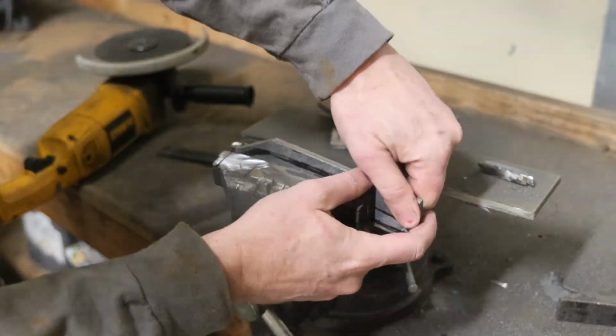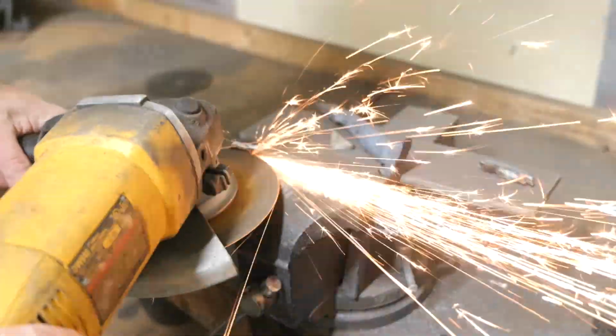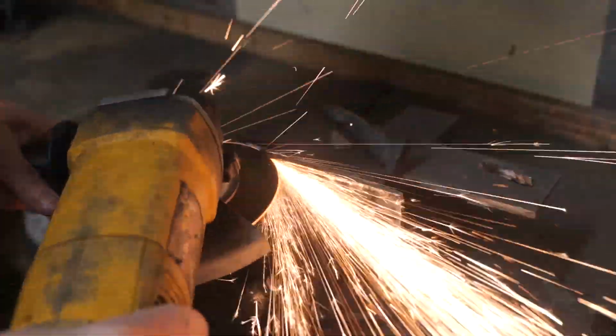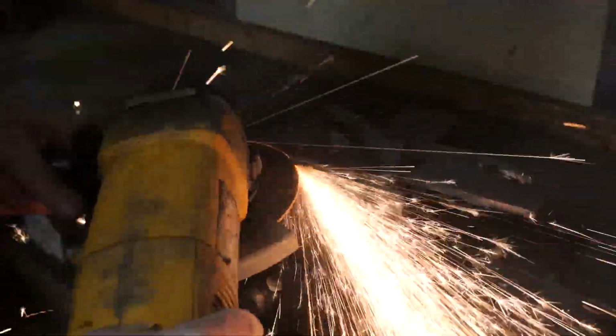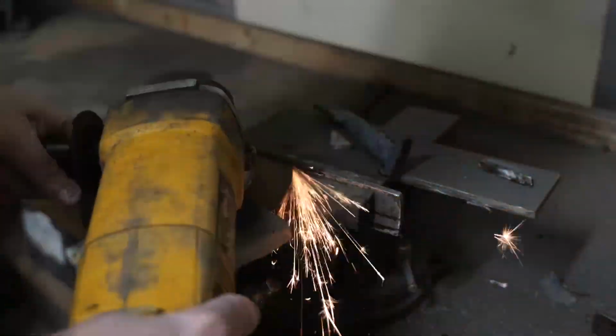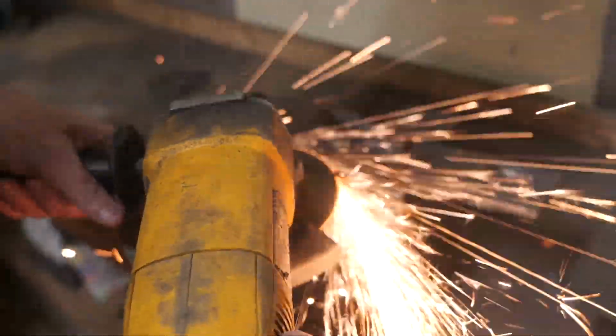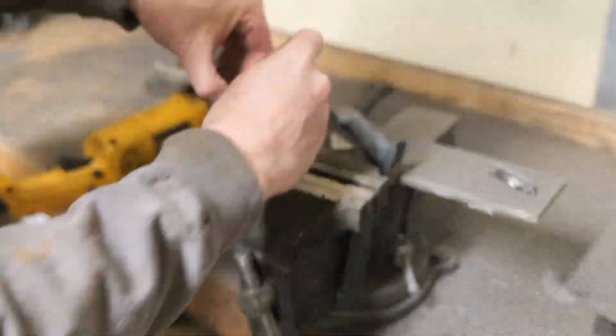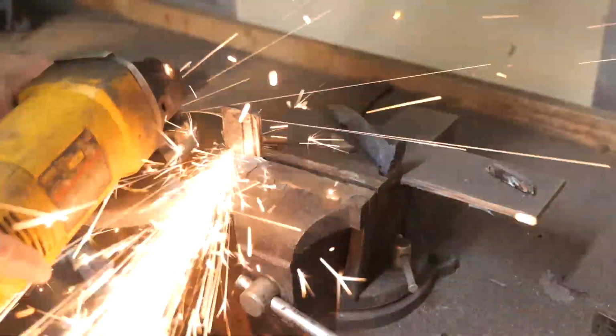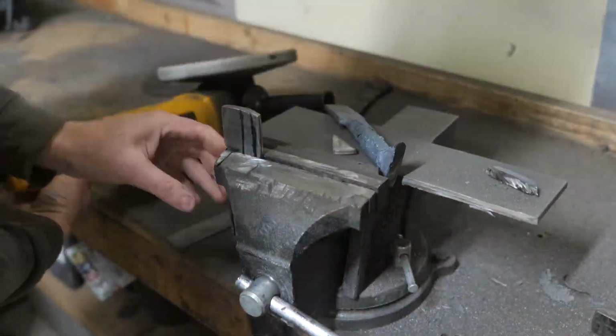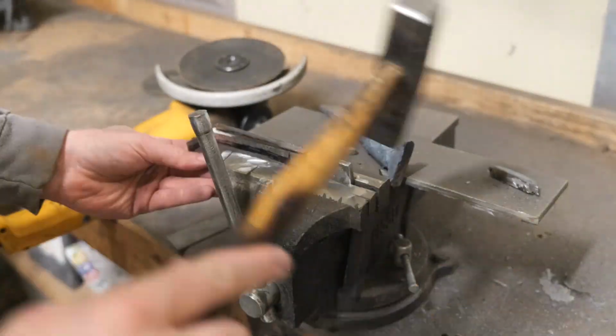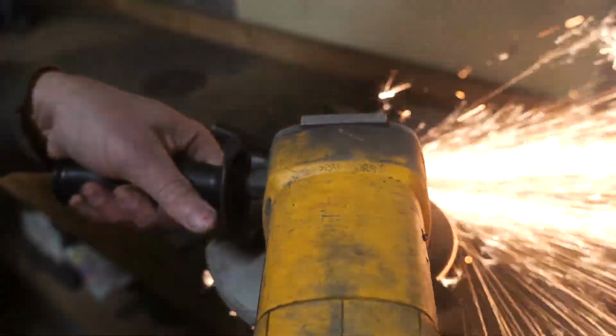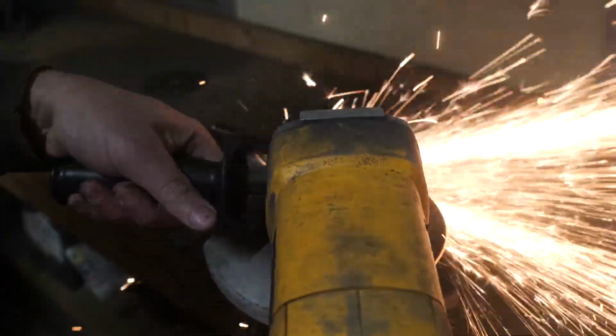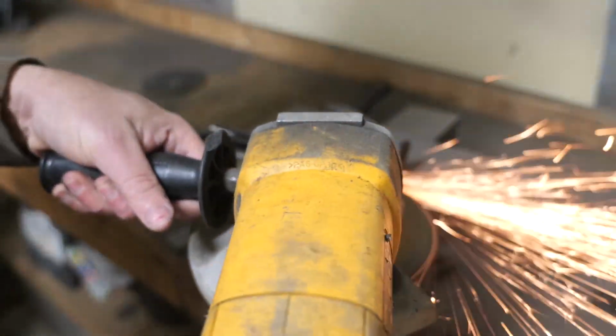But I think there are other issues with forging the stainless and the core. You know, they react differently at different temperatures. You can introduce a lot of stresses and things if you forge this too cold. And then I really don't want to knock the core off center by forging on the blade. That shouldn't be too difficult to avoid, but I don't know why I would risk it. We have enough material. It's just easier to grind most of this to shape. We are going to forge some of the tang a little bit. We're going to have to draw that out.